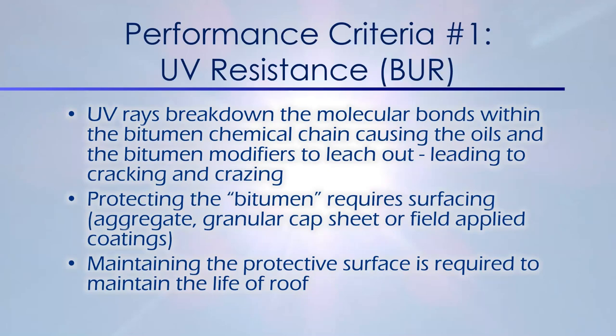Rays of the sun. So when we look at built-up roofs in regard to UV resistance, the UV rays break down the molecular bonds within that bitumen, and the chemical change causes the oils of the bitumen to leach out over time, in addition to those modifiers. What happens with that is what we call alligatoring or cracking or crazing on the roof.